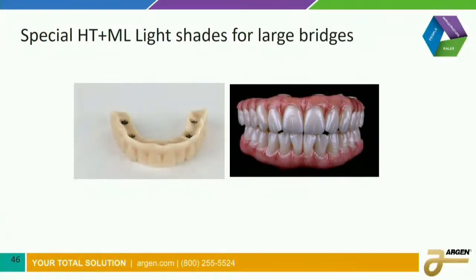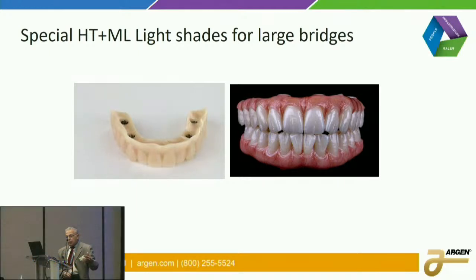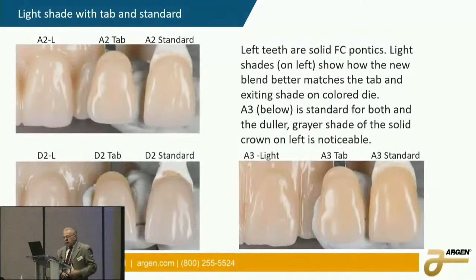Now, one of the things that we did recognize is that the large span bridges, especially the all-on-4 bridges, change the shade of the material because of the thickness of the zirconia. The thicker the zirconia, the less light goes through it, so we have to modify the composition of the coloring oxides. And we've done that, and now we have light shades.